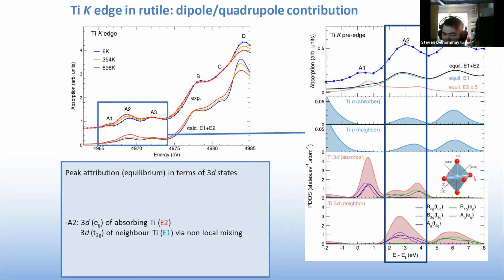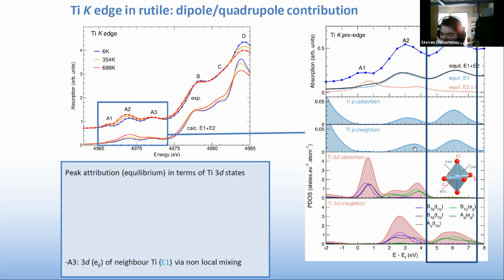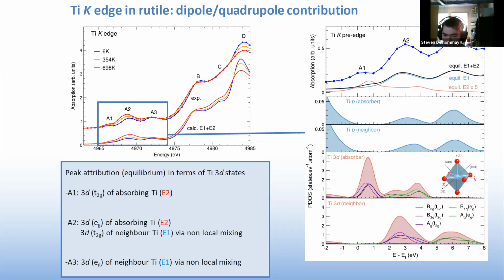And by doing the same work for the third peak, we can see that it is purely a signature of the 3d eg states of the neighboring titanium atom via mixing with the absorbing titanium P states. And so we have this well-known, now relatively well-known, separation between transition meaning for each peak.